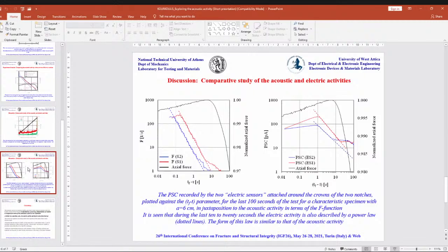For example, the electric signal measured is of the order of some picoamperes. And if we try to apply this out of the laboratory, we have, as you understand, noise. In fact, the electric technique started from attempts to make prognosis for earthquakes 30 or 40 years back. It's not our invention. However, the results are not generally accepted. We cannot make prognosis about upcoming earthquakes. However, the underlying principle exists. While we have microcracking, we have generation of electric signals. So if we somehow manage to calibrate these signals correctly against a mature technique like acoustic emission, then we will have an additional tool that is very cheap and very easy. The setup is very simple. Okay. But not yet.